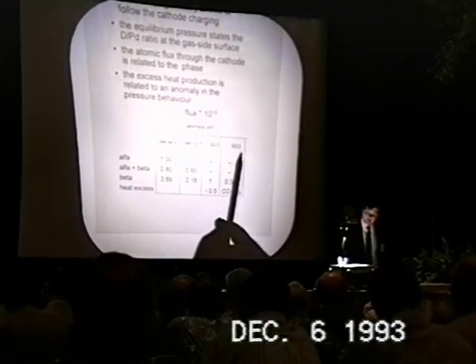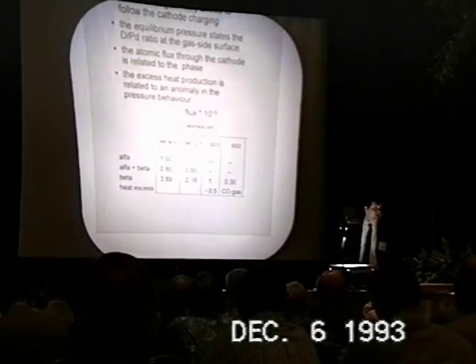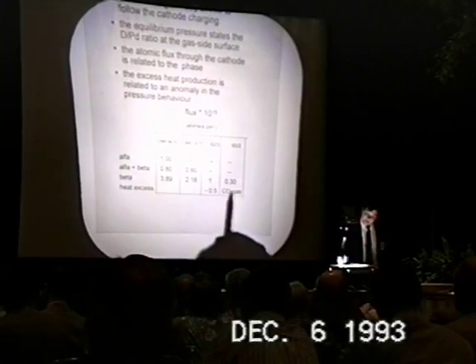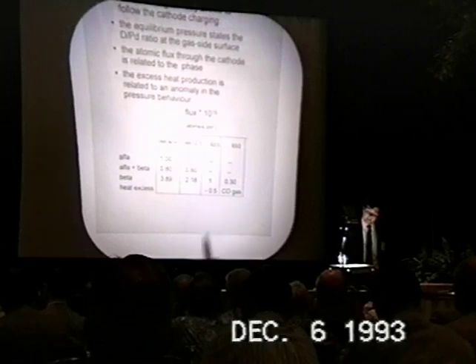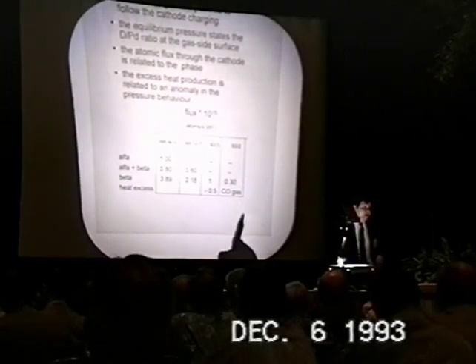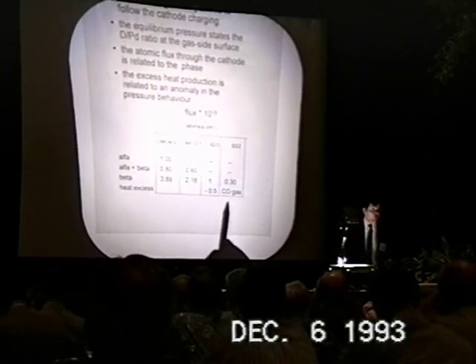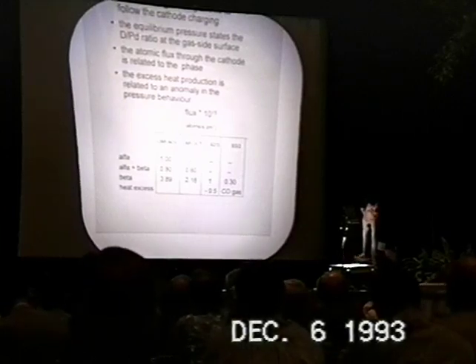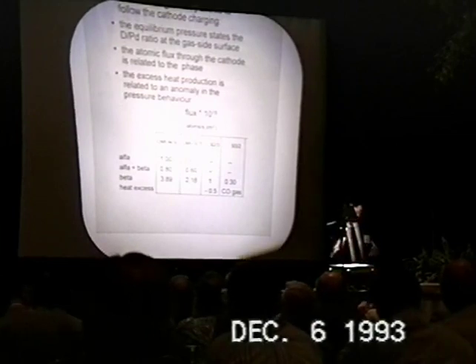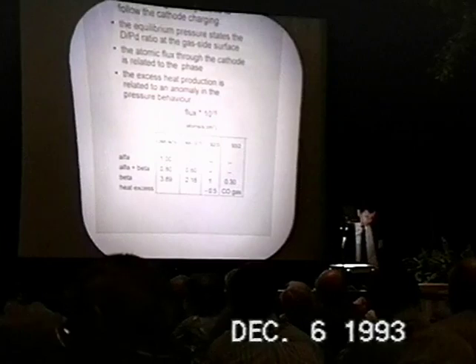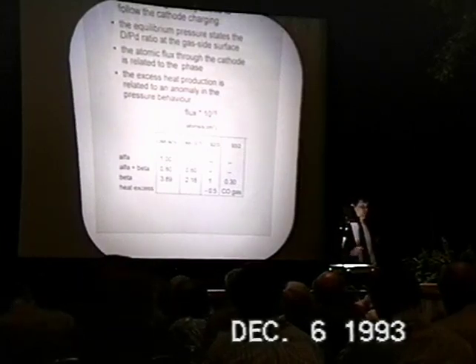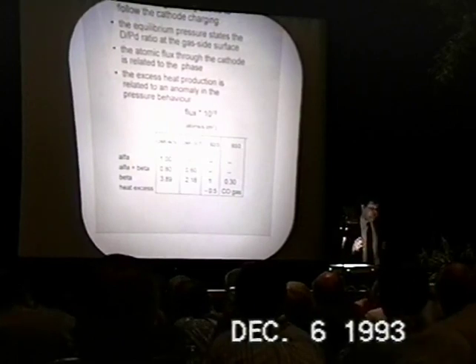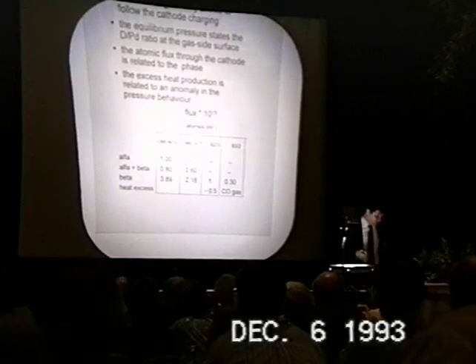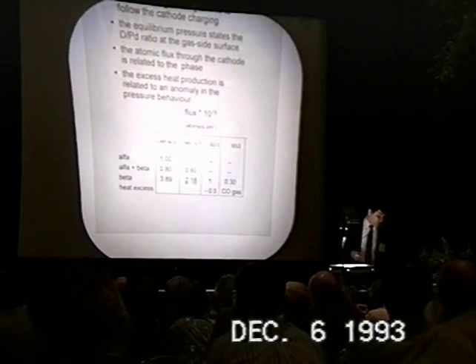The 93 2 experiment is the only experiment with heat excess production, and we have seen a beta phase clearly, and then before heat excess appeared, we poisoned the gas side surface with the CO because we were interested to see the behavior. From this analysis, we believe that the flux variation is surely correlated with the phase change in the cathode. We are trying to do at the same time X-ray measurements on the electrolysis side.